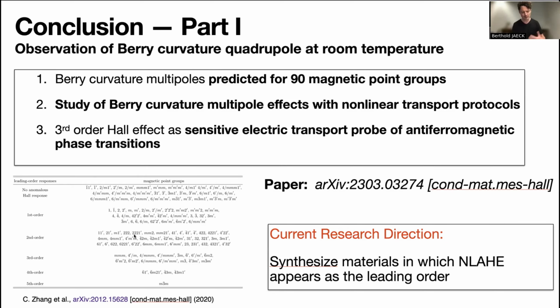And more broadly, what we believe our study really does is open a door to study these multipole effects on various material properties, on the optical, but also thermal properties, using nonlinear transport protocols. From a practical viewpoint, what is quite nice about this work is that it also shows that the third order Hall effect is very sensitive to the antiferromagnetic phase transition. So we anticipate that under certain circumstances, such a higher order Hall effect could be quite useful to characterize antiferromagnetic phase transitions using transport measurements, which often is quite challenging.